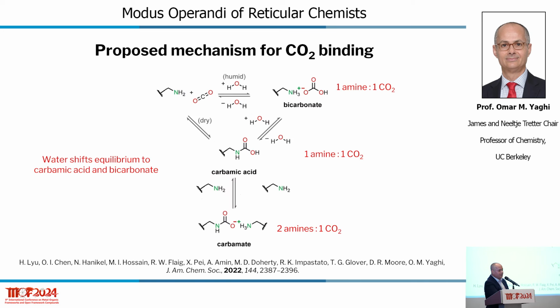But we learned from these experiments that in fact water in the air helps us in shifting the equilibrium towards bicarbonate and carbamic acid. And therefore, for each amine, we can bind one CO2, instead of the dry conditions where two amines bind to one CO2. So water helps us in the carbon capture problem.